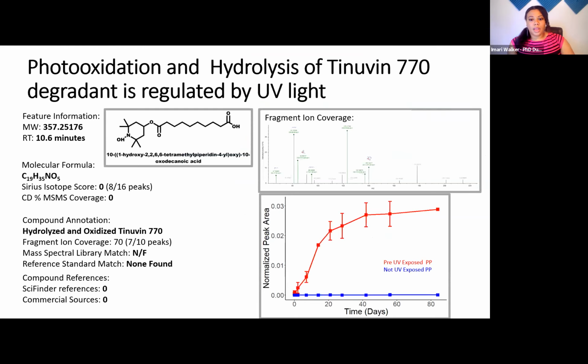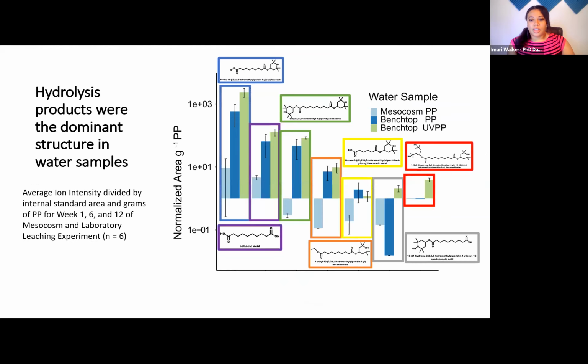So there's quite a few different transformation products that can happen to just one compound itself that's commonly found, especially within this polypropylene. And you can see when you compare the mesocosm water to the actual benchtop studies, there's quite a bit less of it present per gram of polypropylene. And that's probably due to other factors like loss due to absorption or loss of the microplastics deeper into the water column. And it just really shows that even UV light has a pretty profound impact on the release of these compounds and a driver or even regulates the actual presence of certain compounds as well.